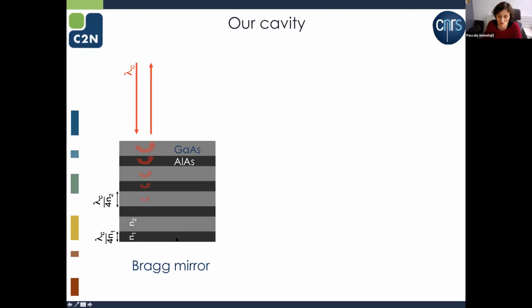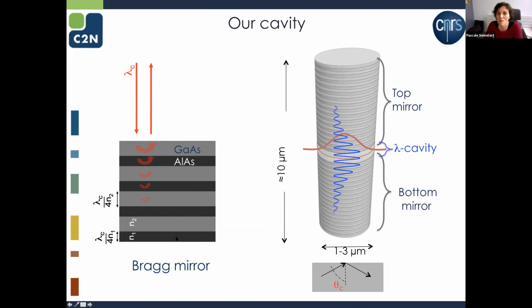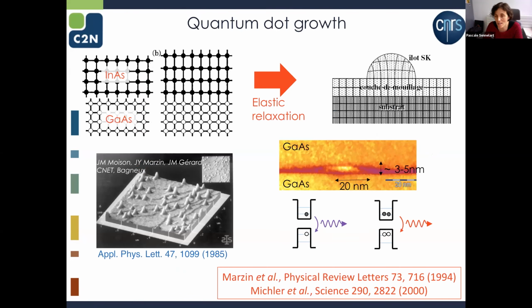So this is the first ingredient. I build a Bragg mirror with that. I will take two of these Bragg mirrors, pile them on top of each other with a spacer in between, and this will define a Fabry-Perot cavity, a lambda cavity that confines light in the vertical direction. Then what we will do is etch this to form what we call a micropillar, which has a few microns in the other direction. And when we do that, we also have confinement in the other direction, exactly like in an optical fiber. So this is my cavity. It's going to confine light in all the directions of space. And now what I want is to put the quantum dot at the center of the cavity.